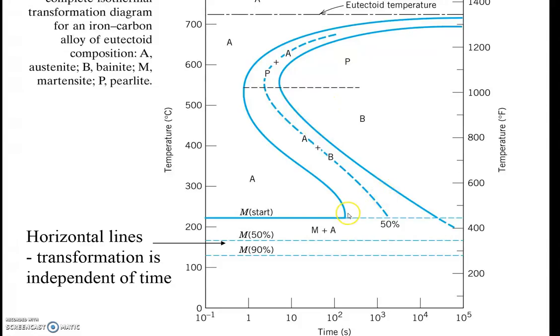So if we are at low temperatures, we have low rates of diffusion, which means that our grains are not going to grow, or lamellae will not grow very thick. So really, you get thinner, fine-grained bainite at the low temperature here, and at this point here, you'd have coarse-grained bainite.